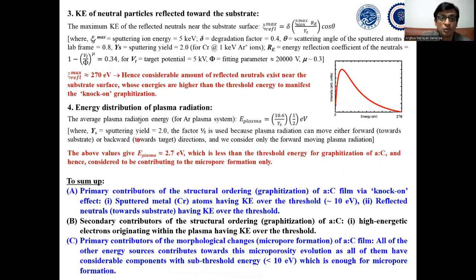And finally, we did the theoretical analysis for the energy distribution of plasma radiation, and we see that the plasma radiation average energy is around 2.7 electron volt, which is less than the threshold energy of the graphitization of amorphous carbon, which is 10 electron volt. Therefore, this is mainly considered to be contributed to the micropores formation.